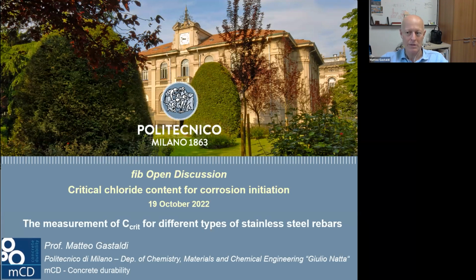And we use also admixture, superplasticizer, that help us. This is the technique that we use because it's not possible when you have an amount of 5% of calcium chloride, you have a setting in a few minutes. So it's not possible to cast 10 samples. For sodium chloride, the problem is not so strong. Fortunately, sodium chloride has no strong effect on setting as for calcium chloride. So for sodium chloride it is not a big problem.